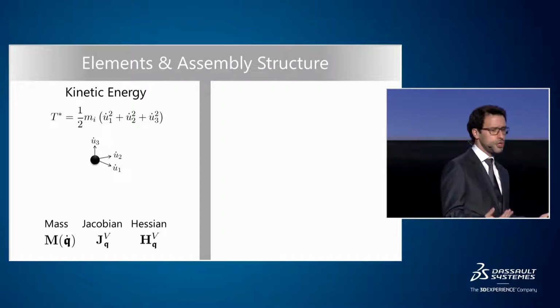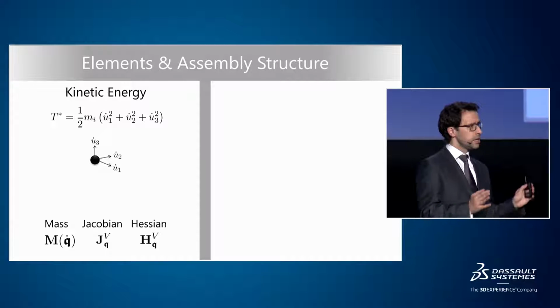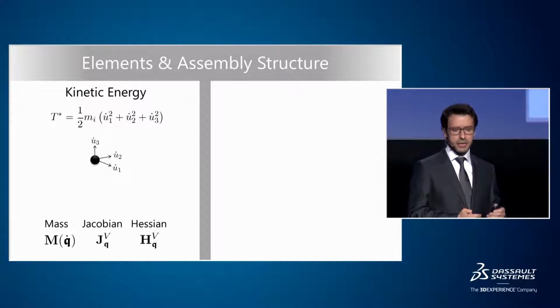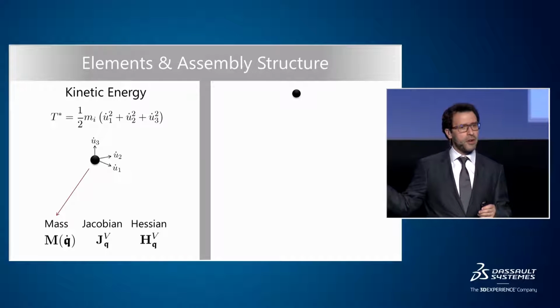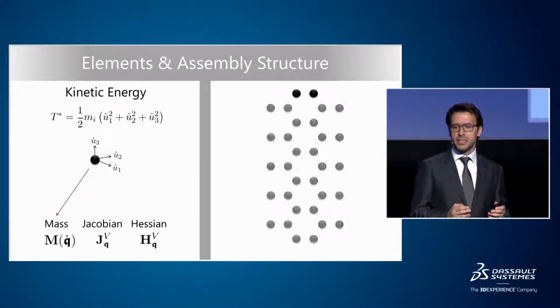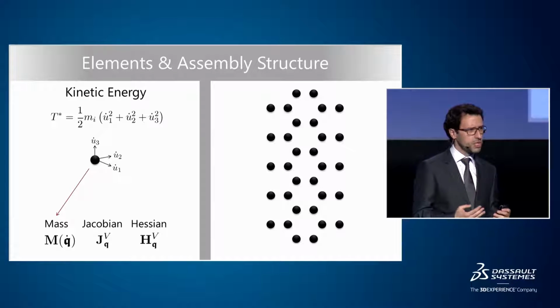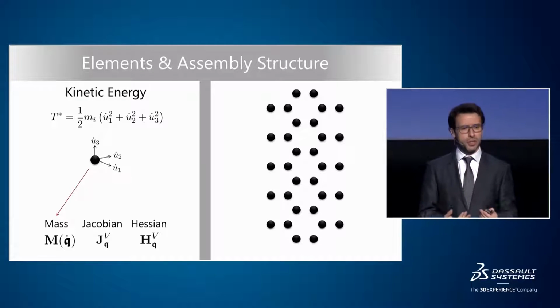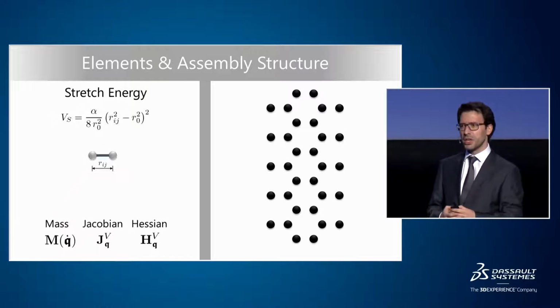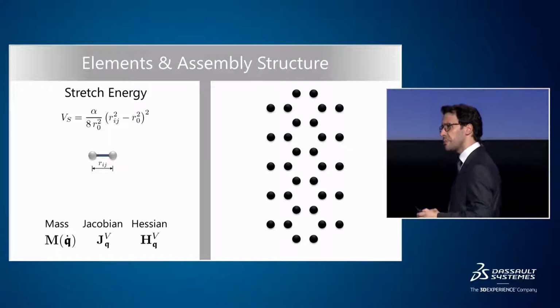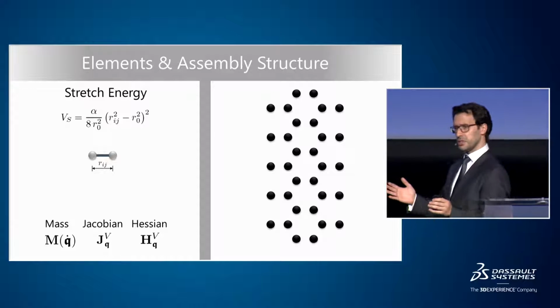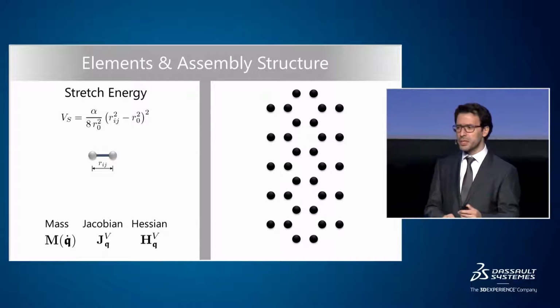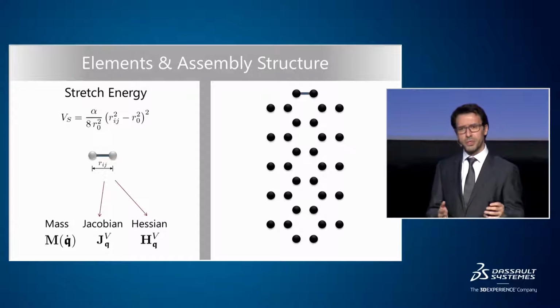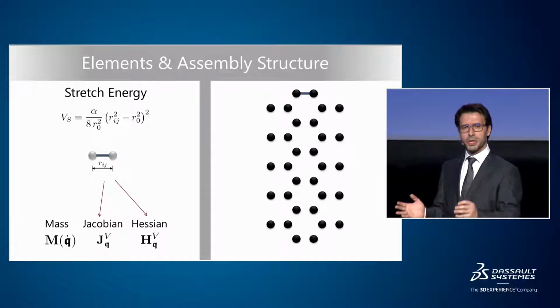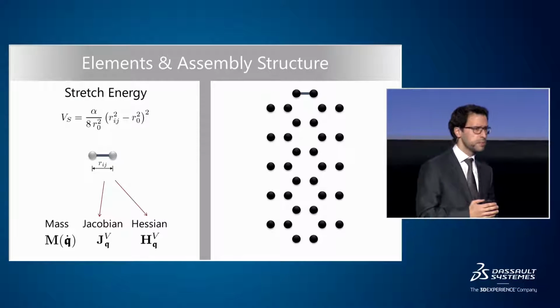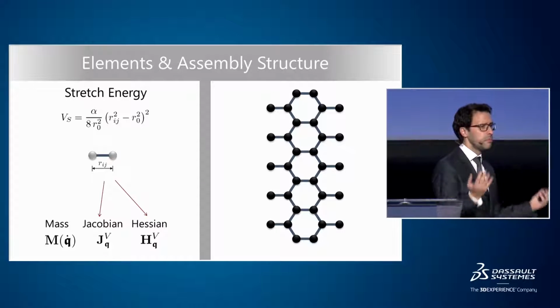So if you think about inertia, for instance, we started by creating one-noded elements, getting their mass, and then for each atom in our structure, seeding that mass and assembling everything into our mass matrix. So at this stage, we have many elements, and we only have inertia in our system. The next step is to look at the force fields that you have in molecular dynamics. Force fields are typically additive, and you start, for instance, with some terms which involve only two atoms. We can represent that with two-noded elements, from which we obtain the Jacobian and the Hessian, so the stiffness and tangent stiffness matrices effectively, and we can mesh these everywhere.